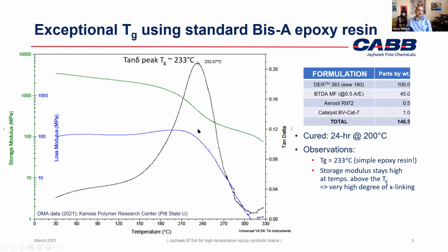Typically, you expect at least a 2 or 3 orders of magnitude drop in the storage modulus at TG, but this system is extremely high in cross-link density, so your modulus drops barely an order of magnitude at around the TG. And that's another indication that it's a very, very highly cross-linked system, to the extent we help our customer base to formulate the products properly to take off the brittleness that may come from that cross-link density.